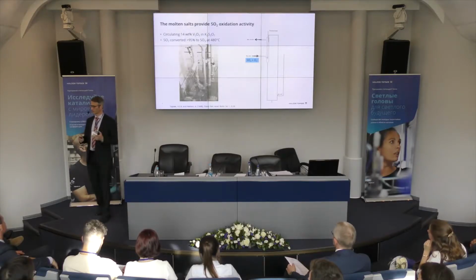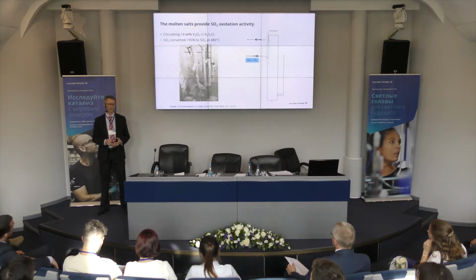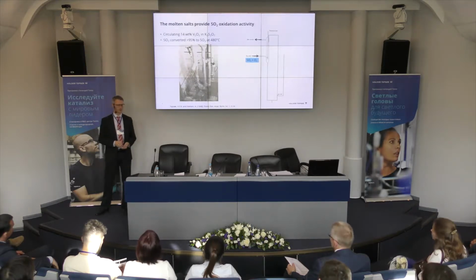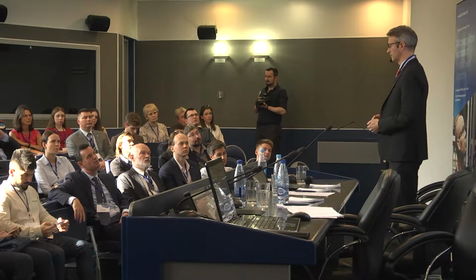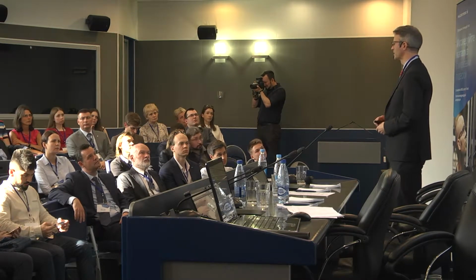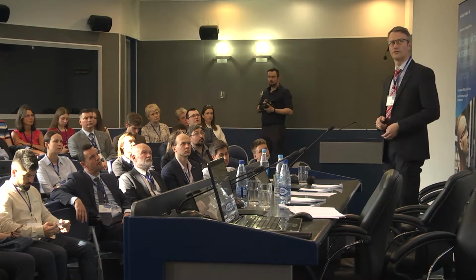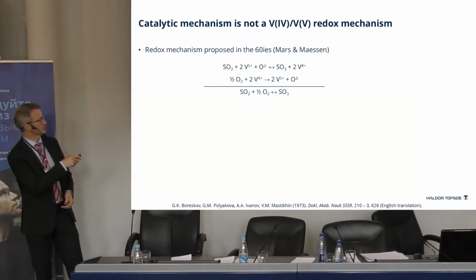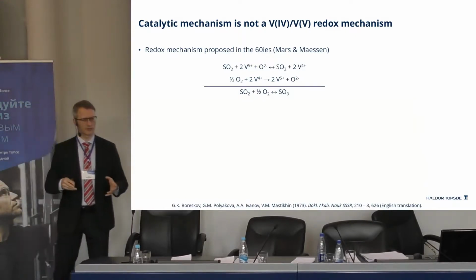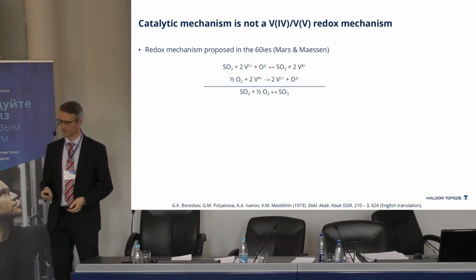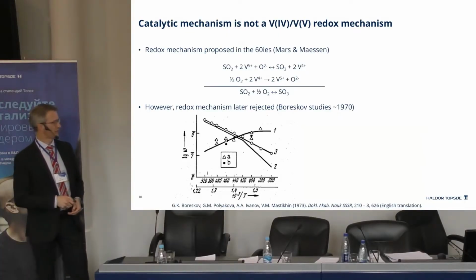Since then, many research groups have worked on understanding the mechanism and the complex chemistry taking place in this system, and we've come far, but it's of course not all understood yet. In the 60s, Mars and Maessen proposed a redox mechanism that was discussed for many years, where you can see the SO2 is oxidized to SO3, vanadium is reduced, and then vanadium is reoxidized afterwards by oxygen. However, later studies showed that this could not be the governing mechanism for this catalyst, and many of them were done by Boreskov and co-workers around 1970.